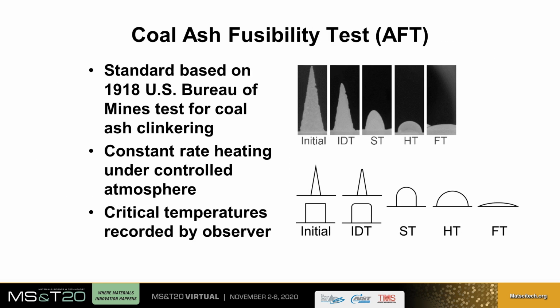It is one thing to predict the effective viscosity of pyrometric cones, which are formulated with a handful of carefully selected minerals and prepared in large batches with consistency as a key performance objective. How well does the thermophysical modeling approach work with the coal ash fusibility test, which must contend with a much wider range of mineral compositions? The coal ash fusibility test, or AFT, was inspired by pyrometric cones as a way of measuring the propensity for coal ash clinkering. The AFT critical temperatures figure prominently in the assessment of coal quality even today.